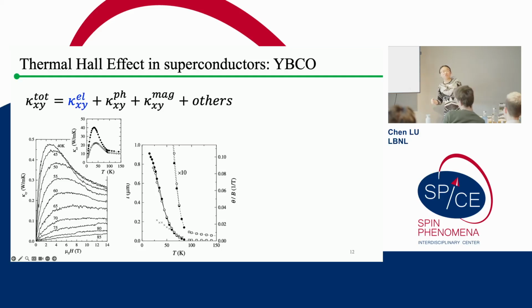So for this kind of cuprate materials, once the temperature goes below TC, electrons form Cooper pairs. So Cooper pairs do not carry heat. They don't carry entropy. However, for this particular type of cuprates, there are the so-called D-wave superconductors, which means you will have a special type of quasi-particles called D-wave quasi-particles that can still carry heat for you inside the superconducting state.